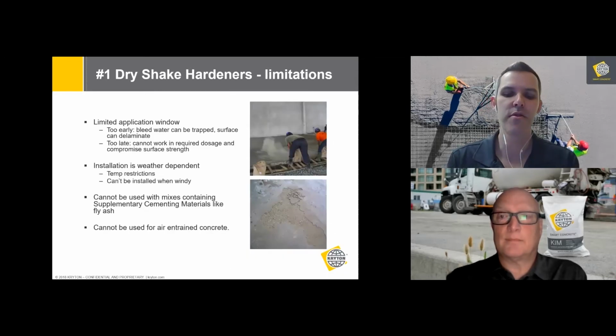So some of the challenges they're going to have. These dry shakes are very sensitive to the bleed water on your concrete. You need just the right amount of bleed water at just the right time. If they apply the products too soon, when they trowel it in, they trap the bleed water, and this can cause delamination in their surface. If they wait too late, the concrete slab will simply set too much, and it just won't accept the dry shake. They can't get the full specified amount applied to the concrete.